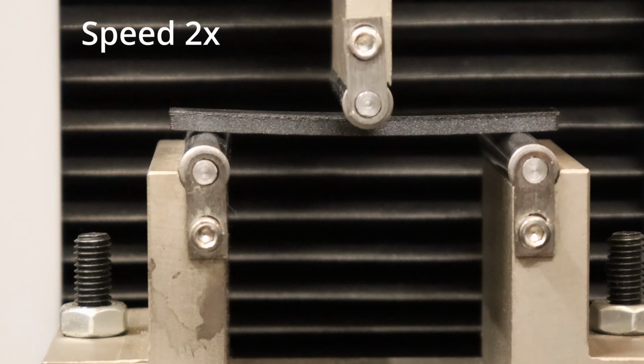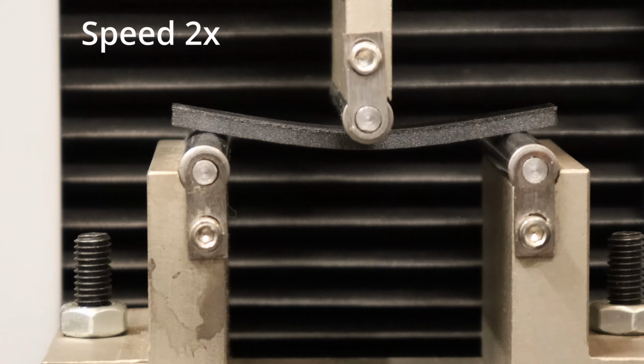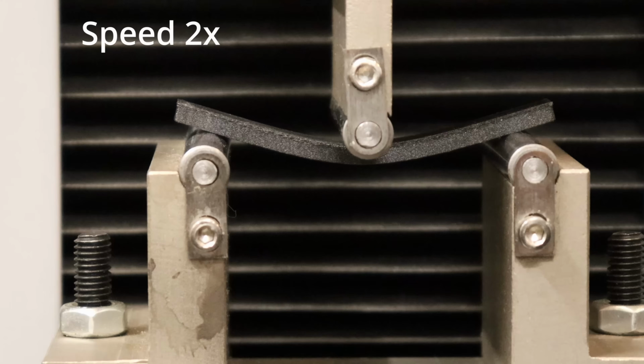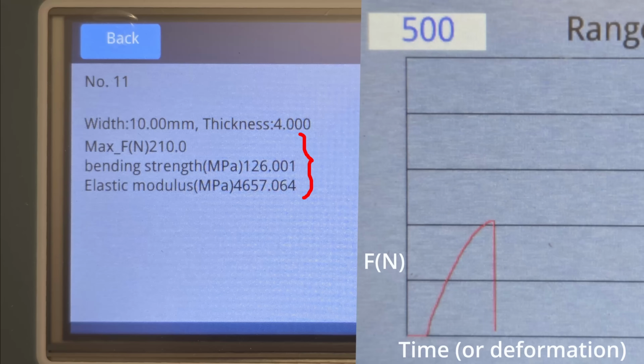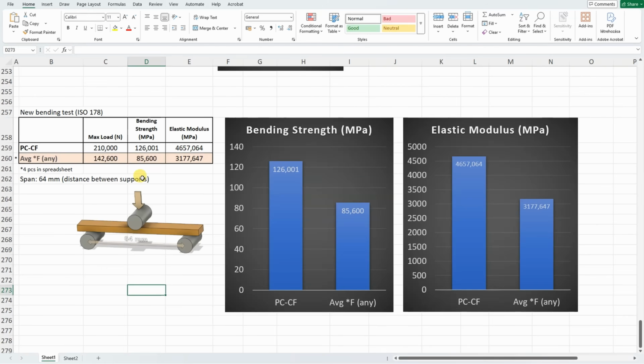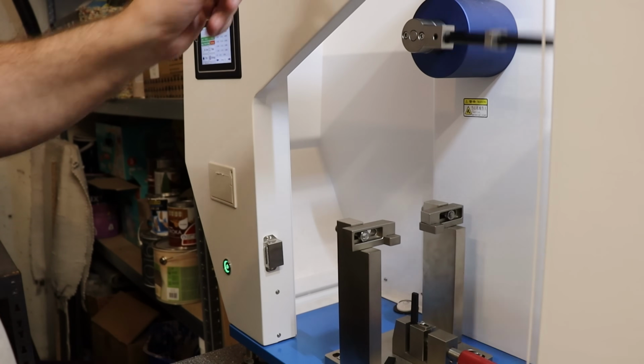Another 3-point bending test, sped up 2 times. And it breaks suddenly. And here is the graph: max load, bending strength and elastic modulus. Another test which I started much later, and I don't have enough data. I have only 4 pieces of fiber reinforced filaments, and not just PET, in that summary table when I am recording this video. Compared to that one, this PC-CF is stronger in both bending strength and elastic modulus, which depends on the deformation too.